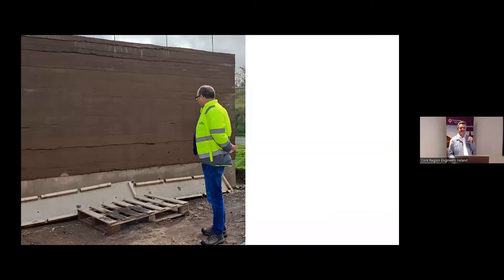This is a great photograph of an engineer inspecting the wall — it has a beautiful material quality. The earth changes with the seasons: in summer it gets really dry and almost has a dusty feeling, while in winter it absorbs water and darkens. It really responds to environmental conditions. This is when we'd taken down all the formwork. You can see from the lines as we got to the top — we learned from our first wall that we had too much pressure, causing it to bulge slightly at the top. But overall, we were happy given it was our first major wall.